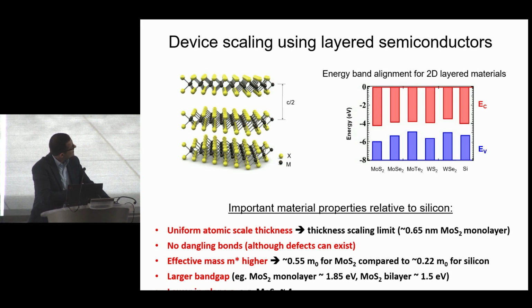There is a large library of 2D materials, and here I'm just showing a small subset of these monolayer semiconductors. They all have different band gaps, they have different band alignments. And I think from a maturity point of view, probably the two that are most promising would be tungsten diselenide. This would be the ideal material for PFETs, and moly sulfide. This would be the ideal material for NFETs.